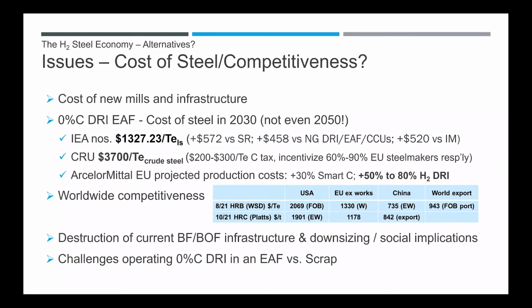The next issue is cost of steel. Not only do we have the cost of new mills and infrastructure, but the zero carbon DRI is going to make steel cost $1,327 a ton of liquid steel if you use the IEA numbers. And this is at 2030, not even 2050. CRU, on the other hand, say that it's going to be $3,700 per ton of crude steel. And they're looking at $200 to $300 per ton of carbon tax, which would incentivize 60 to 90% of the steel makers in Europe, respectively.